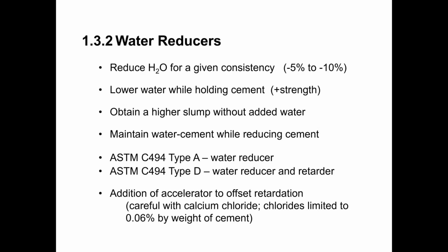ASTMs which cover water reducers are type A and type D of ASTM C494. The difference between a type A and a type D water reducer is that a type D water reducer also has some retarding effects. So keep that in mind. If you're using a type D water reducer, there may be some delayed strength gain early on during initial curing. So just be prepared for that. In some instances, that may be to your advantage.